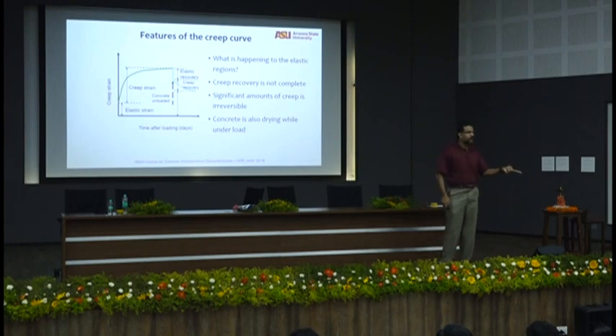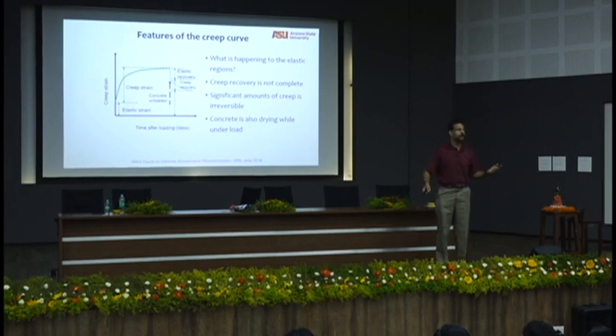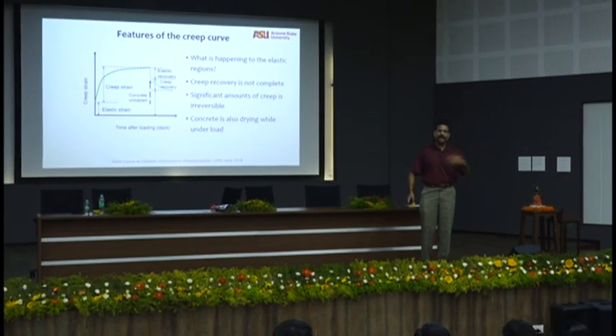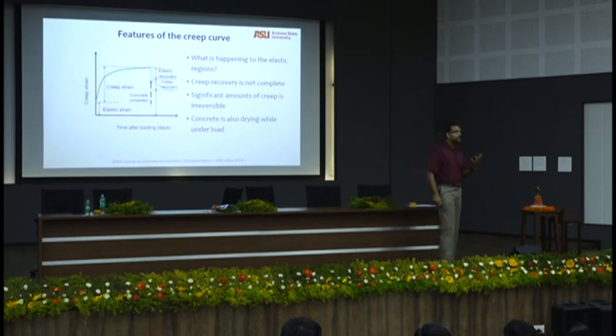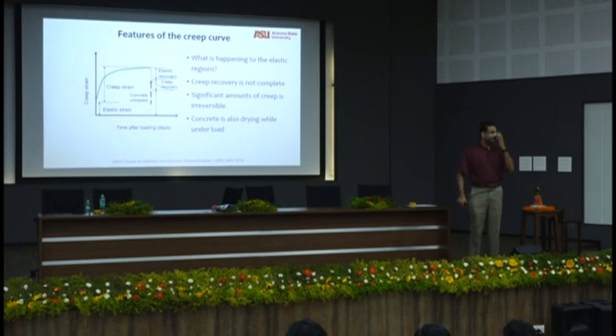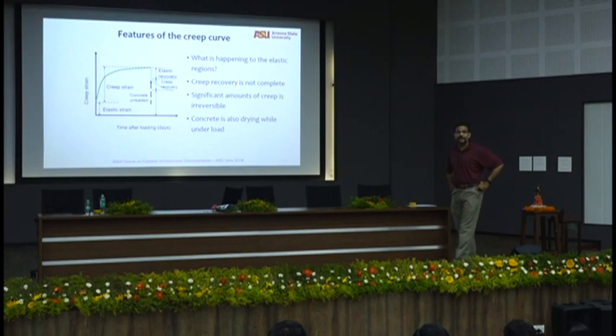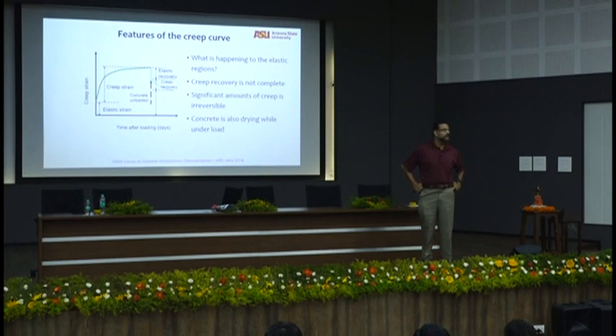You have a high elastic modulus, is it going to relax? Low elastic modulus, low stiffness, you may have a chance. That is why you must try to do a balance. Now, you will tell me, yes, I want a low elastic modulus, therefore I will throw in rubber tires in concrete, I will throw in whatever soft particles in concrete, that will reduce my elastic modulus of concrete. And then I'll put in a very strong cement paste, and then I'll throw in these to reduce the elastic modulus of concrete. Will it help?